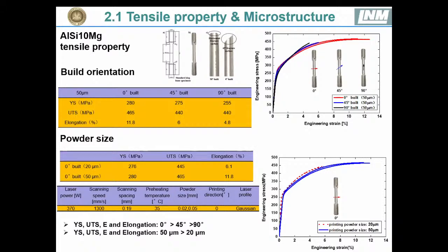And here shows the result for the tensile test. Here we can see that the build orientation has a strong effect on the yield stress, ultimate tensile stress, and the elongation. We can see that the 0 degree build specimen has a higher yield stress and also a higher ultimate tensile stress than the 45 degree build and also the 90 degree build. The powder size also has a strong effect on the property. Here we can see that the specimen built with 50 micron powder is higher than that with 20 micron. The reason will be clarified later.